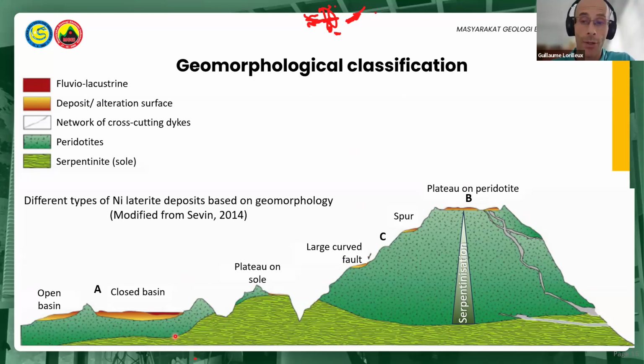Basin deposits can be very large and characterized by a typical flat morphology with low relief surrounded by crest lines. Plateau deposits are generally large deposits located in plateaus or mountainous, elevated areas. Continuous plateaus are less impacted by erosion than dissected plateaus. In continuous plateaus, the topmost resistant ferricrete is continuous, and it armors and protects the softer underlying horizons from erosion. In these deposits, oxide and hydrous magnesium silicate ore coexist. In dissected plateaus, most of the upper part of the weathering profile has been eroded. In this case, hydrous magnesium silicate ore is predominant in these deposits.